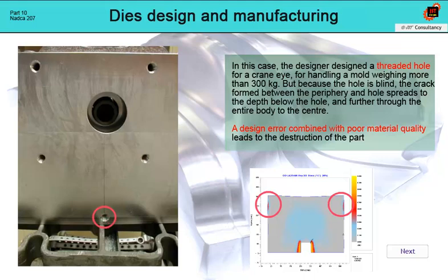Its location is in the photo. At the place of the threaded hole, a crack appeared between the hole and the periphery of the body. Since the insert was made of H11 unremelted steel, with many impurities, with a gross austenitic grain, size 4 and 5, the material's resistance to crack propagation was significantly reduced.